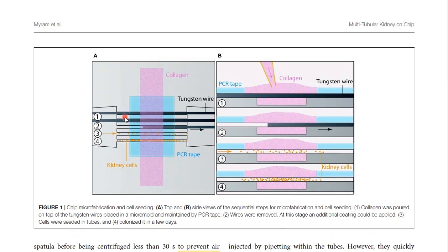In these separations, the wires are going to be positioned to mold the tubes. Two connectors with a semi-cylindrical bottom at the side of the COC plate were placed at both extremities of those rows with a continuous transition. Liquids and cells were injected through those two connectors. In order to obtain an adequate covalent attachment of collagen 1, the COC reservoir surface was first treated with oxygen plasma.